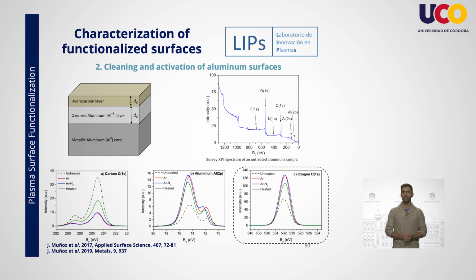By observing the individual signals, it can be seen that the post-discharge treatment generates a decrease in carbon and an increase in oxygen and aluminum. This suggests that this external hydrocarbon layer may be being removed with the treatment. However, this effect, although to a lower extent, is also seen when the sample is heated, so it cannot be the only factor causing the change in wettability.